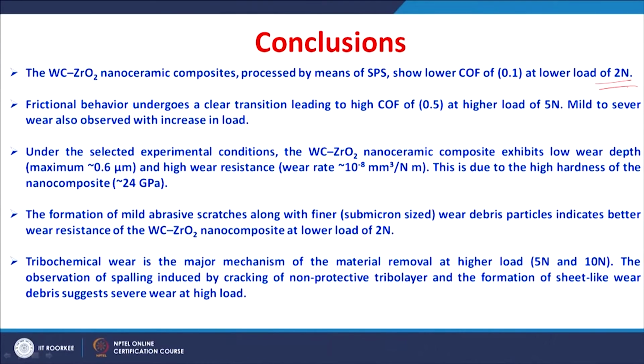Concluding the results obtained on the wear behavior of the tungsten carbide zirconia nanoceramic composite under fretting conditions against steel, a lower coefficient of friction of around 0.1 is observed at a lower load of 2 Newton, whereas the frictional behavior undergoes a clear transition, leading to a higher coefficient of friction of around 0.5 at a higher load of 5 Newton or more. Mild abrasion to severe wear by tribochemical layer formation and its delamination is observed with the increase in the load from 2 Newton to 10 Newton.